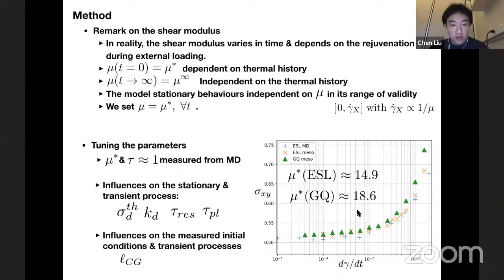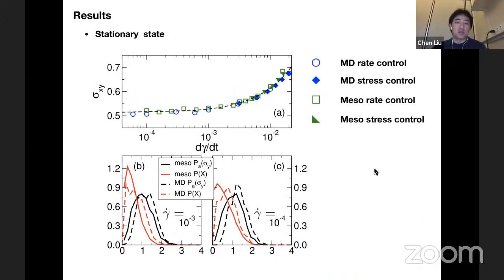So with these parameters, this is the full result of the stationary state. We measured the flow curve from the meso model and from MD with the two types of shearing protocols, and all lines fall on the same line. They agree quite well with each other. We also measured the stationary state apparent distribution of local thresholds, which is the gamma y here, sigma y here, and also the distribution of the distance from local stress to the thresholds for two different shear rates.